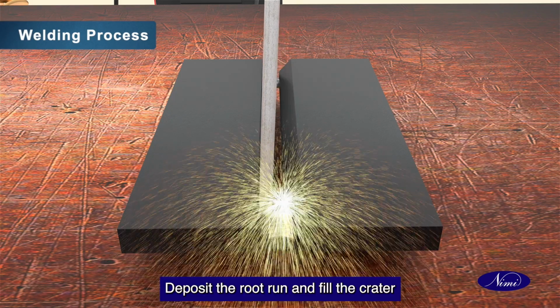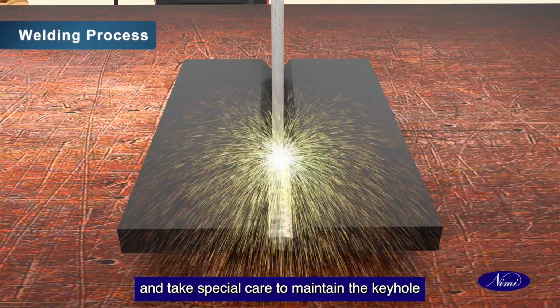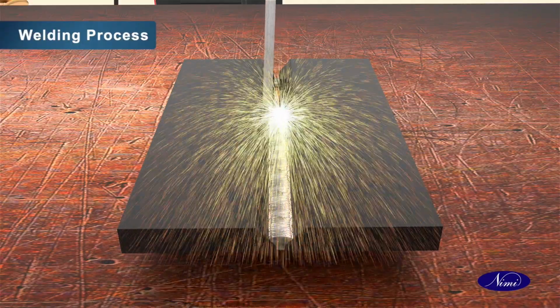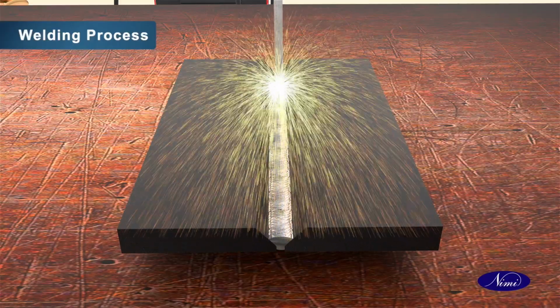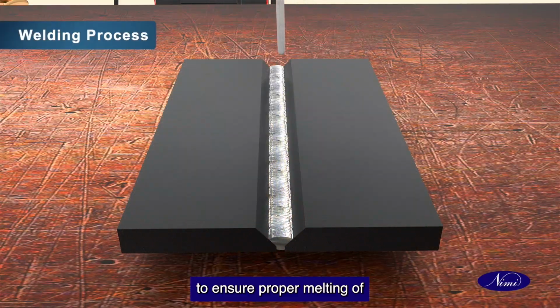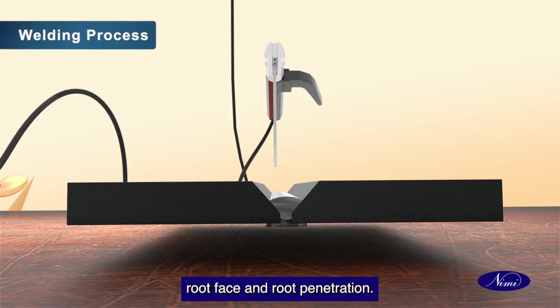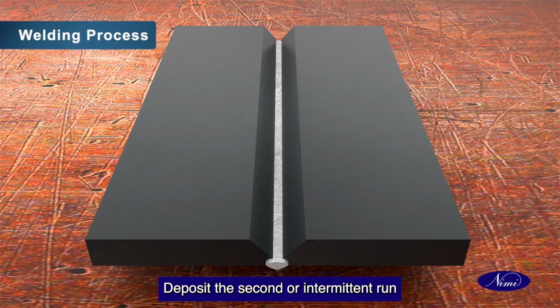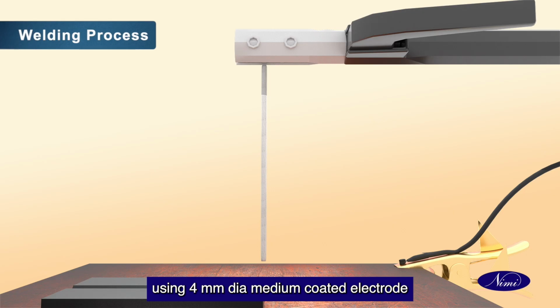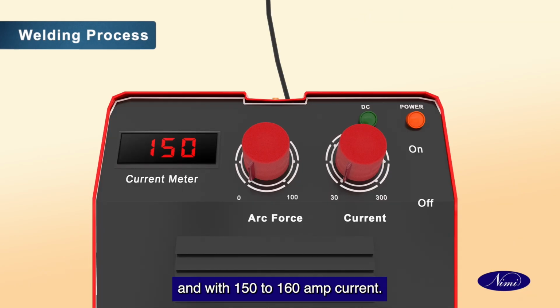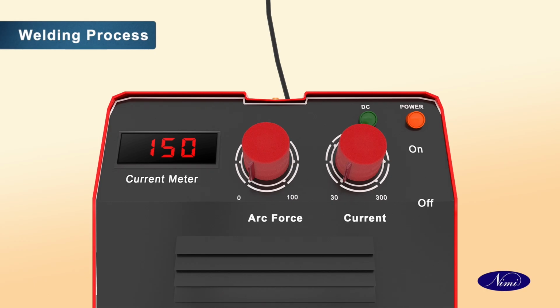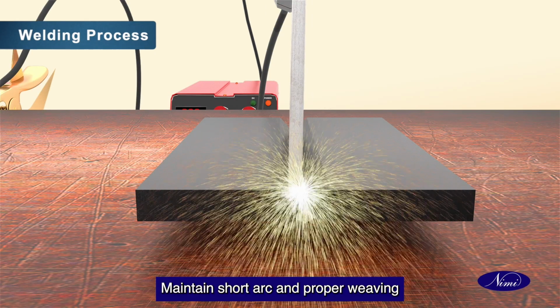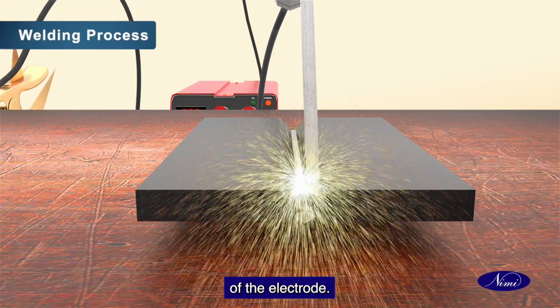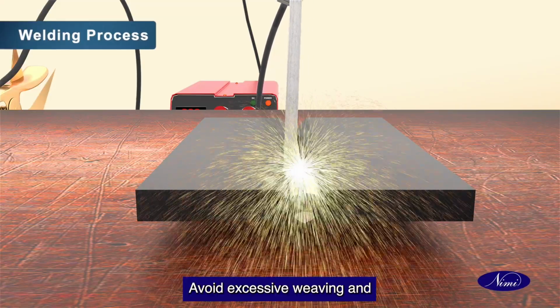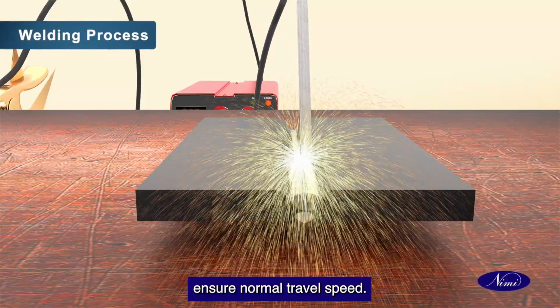Deposit the root run and fill the crater and take special care to maintain the keyhole, to ensure proper melting of root face and root penetration. Deposit the second or intermediate run using 4 mm dia medium coated electrode and with 150 to 160 amp current. Maintain short arc and proper weaving of the electrode. Avoid excessive weaving and ensure normal travel speed.